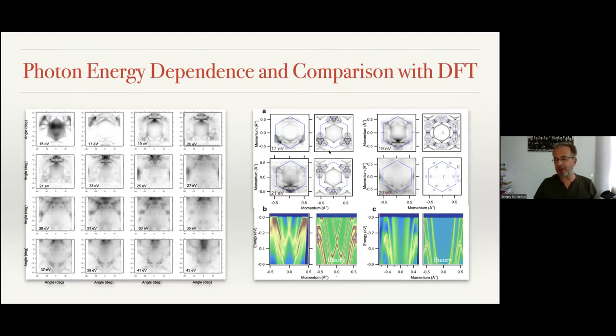By comparing with the calculations and having these many Fermi surface maps, we could figure out at which photon energy we cut the Fermi surface at which Kz. For instance, if you find a certain degree of similarity between the experiment and calculations, in this particular case, you see how this triangular shape, so you have this point and you have the side, and it is flipped in this case, so you could identify approximately where you are in the Kz. I'm saying approximately because the Kz resolution of an ARPES experiment is not as great as Kx, Ky, but in this case, one is still able to do that. So this means we have access to all three momentum components and energy, so fully four-dimensional information about the electronic structure of this material.